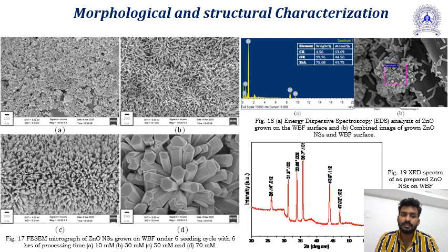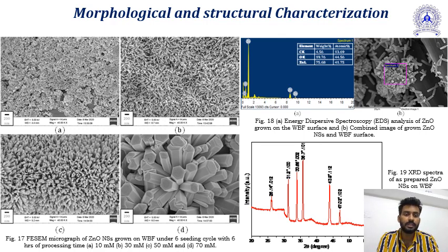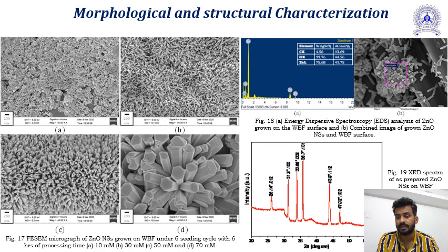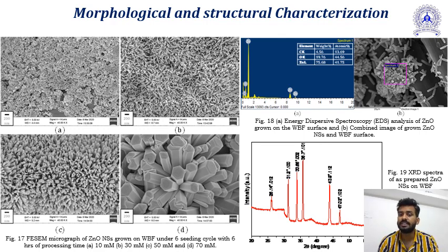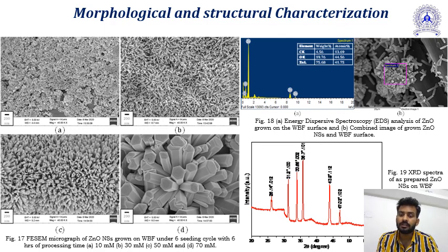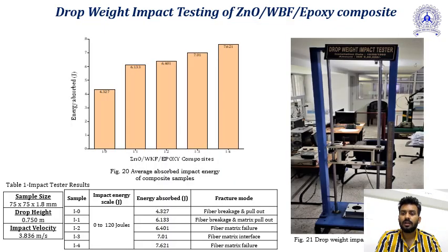Morphological characterization was performed at varying molar concentrations: 10 millimole, 30 millimole, 50 millimole, and 70 millimole — referring to the concentration of growth solution reactants (zinc acetate dihydrate, HMTA, and zinc nitrate hexahydrate). Hexagonal nanostructures were developed. EDS spectra confirmed the presence of enormous amounts of zinc and oxygen on the surface. XRD spectra gave crystalline peaks of ZnO at different angular positions, verifying the presence of ZnO on the surface of the basalt fiber.